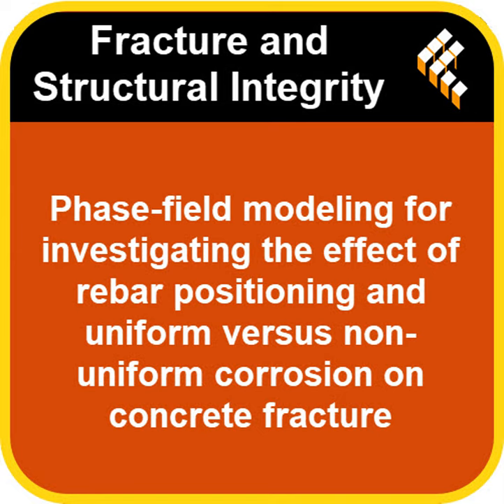Definitely. But specifically for the edge-placed rebars, there was that interesting trend with non-uniform needing less rust at T1 initiation, but significantly more rust to get to T2 propagation compared to uniform corrosion. Especially with thinner covers, you said. Yes, particularly at 10 millimeter and 15 millimeter cover. Then, with the thickest cover, 20 millimeter, that non-uniform case got even more complex because the edge parallel cracks started interacting with hints of that diamond pattern. Wow. So cover thickness doesn't just delay things, it can interact with the corrosion type to change the failure mode. It seems so.